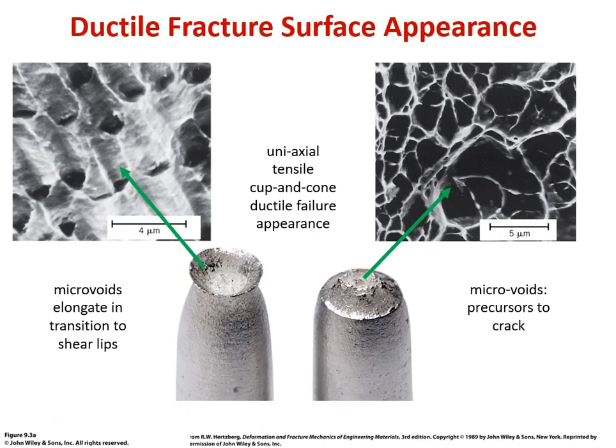But overall, just in terms of the original size of the tensile sample, that failure surface has a lot of topography. And that is characteristic of the amount of plastic deformation that occurred in association with the failure. A lot of the mechanical strain energy that we put into that sample, applied by our tensile tester, went into deforming the material. It could absorb a lot of energy. And so even though we eventually failed it, this is called ductile failure. This material, if it were used in service, could absorb quite a bit of energy before fracturing, and so it would have what we'd call a high fracture toughness.